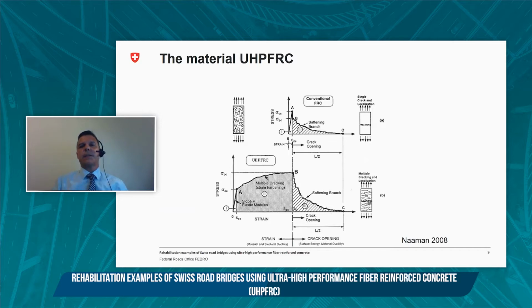Now, let's see in more detail the structural response in tension of ultra-high performance fiber-reinforced concrete and how it is different from that of ordinary concrete with fibers. For ultra-high performance fiber-reinforced concrete, in the first part of the curve until point A, the stress rise is quasi-linear and elastic until the cracking strength. After cracking, strain hardening takes place until point B, with post-cracking strength being higher than that of the cracking strength. Up to point B, multiple cracks are formed during the strain hardening.